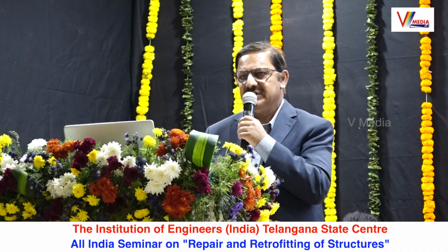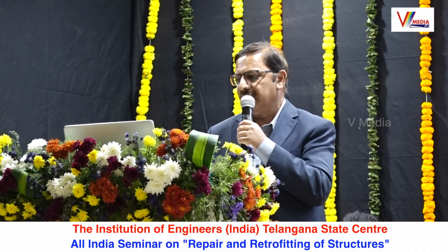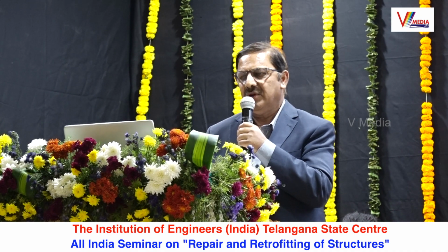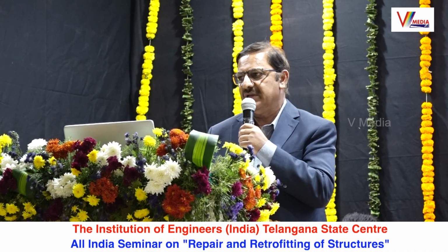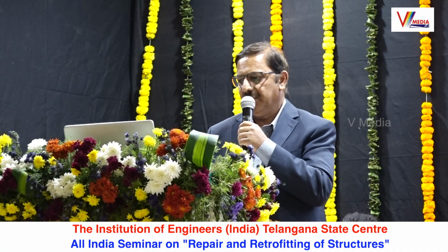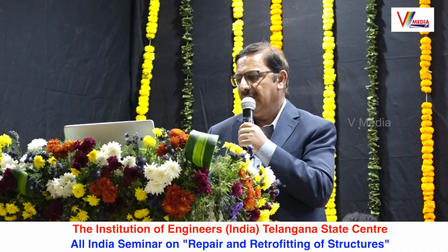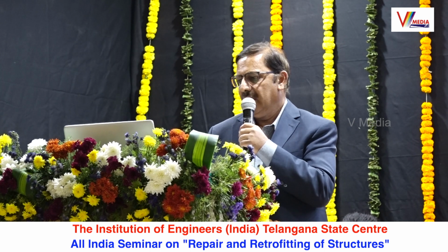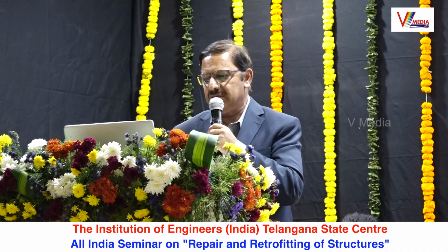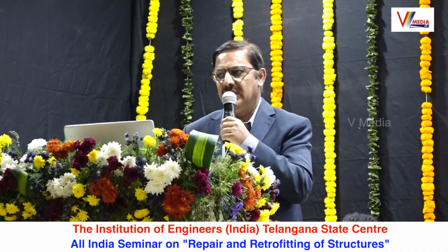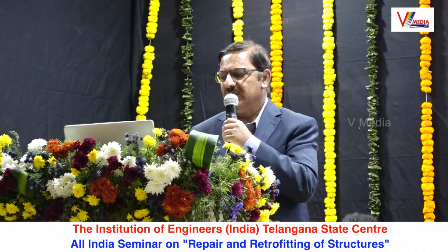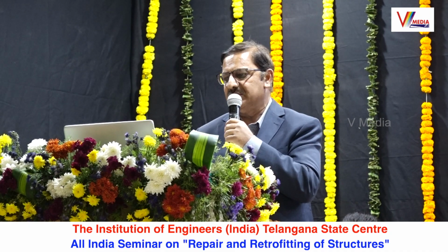Then stainless steel is coming up. Again, this is for critical structures exposed to harsh environments. And there is another technique, mostly used for industrial structures, which is cathodic protection. It's a proven technology that can be designed for a service life of 40 years. The beauty of the technique is that it can be used even if the concrete is contaminated with excessive chloride.